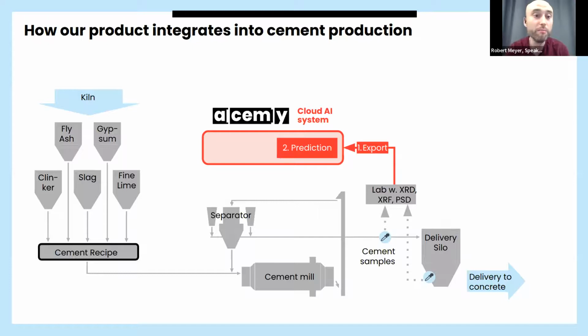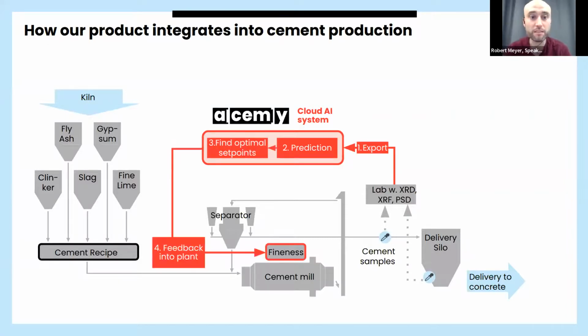And now we can immediately react and don't have to wait a month until the actual strength result is available. If the prediction says you're producing something that's getting too strong, then we can counteract and say, grind more coarsely. So we can calculate optimal fineness set points for the cement mill, feed that back into the plant, and the cement mill will be changed to grind a bit more coarsely. Then 1, 2, or 3 hours later, the next sample is taken, and everything will be on target. This loop runs 24/7 year round in a cement plant in order to get cement strength really on target.